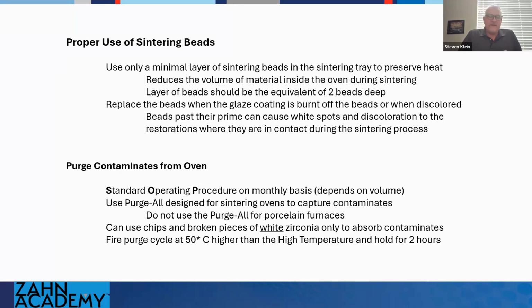You don't have to mess with extra expensive beads, and potentially having a batch or at least 1 or 2 units go bad in a sintering cycle because the beads were already past their prime. So if you do use beads, always use a minimal layer of beads in that sintering tray, because you want to make sure that you're not adding bulk to that firing program, because everything that you put in there robs away from that heating process. So to preserve the heat, go minimal on the amount of beads that go in there.